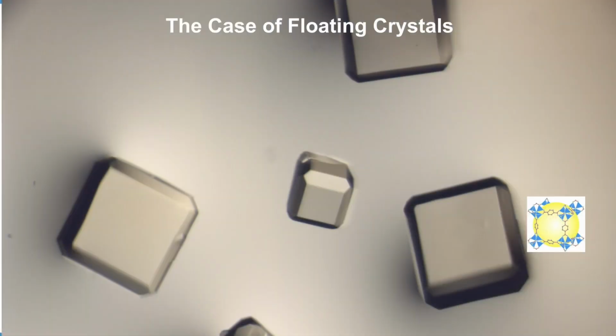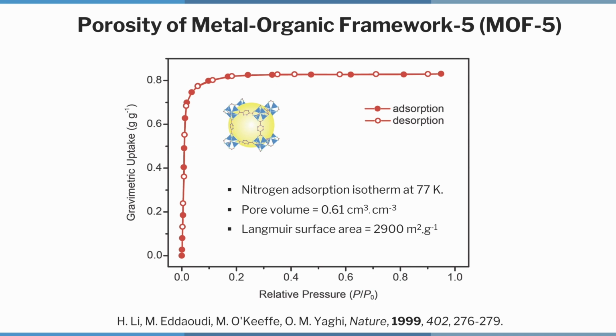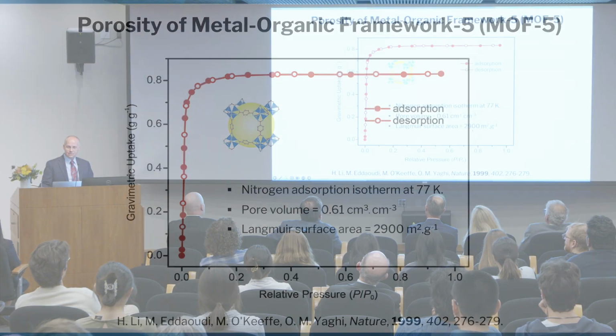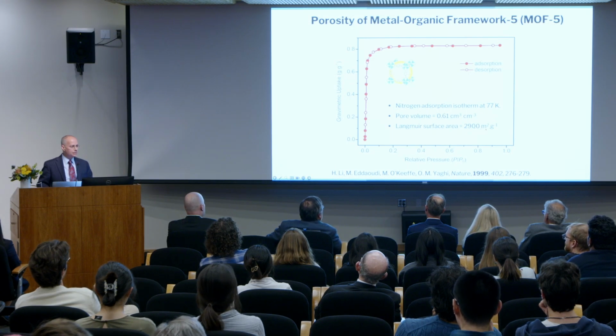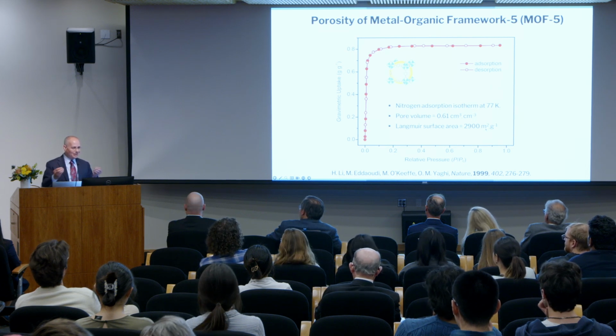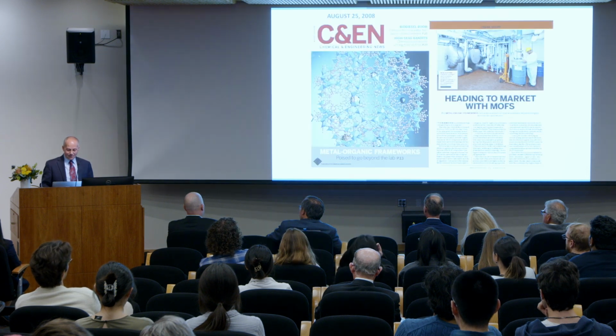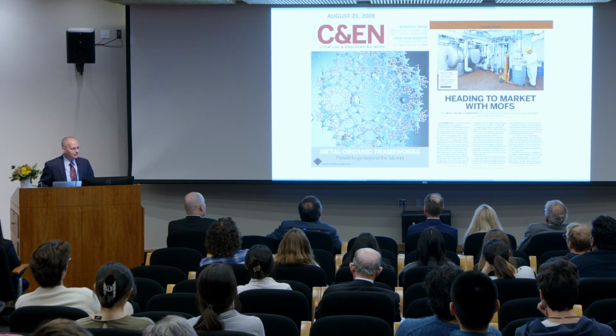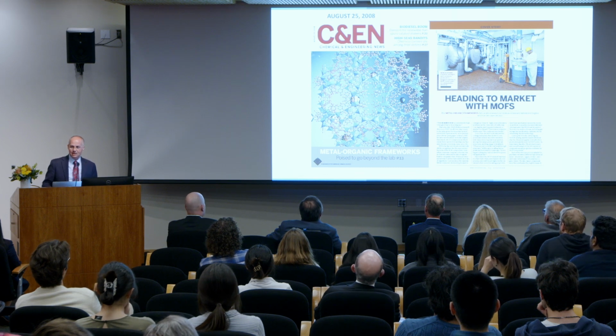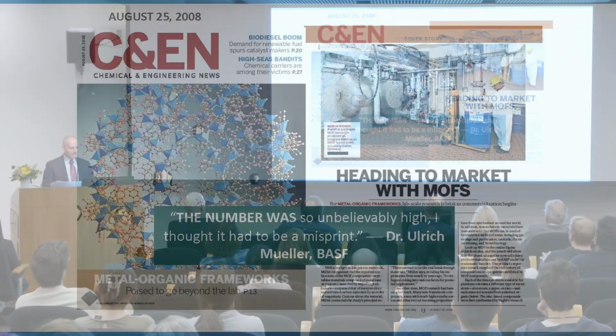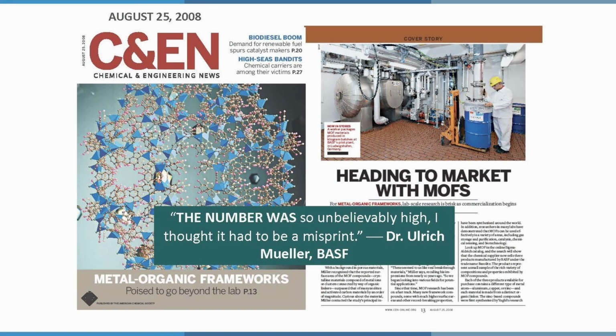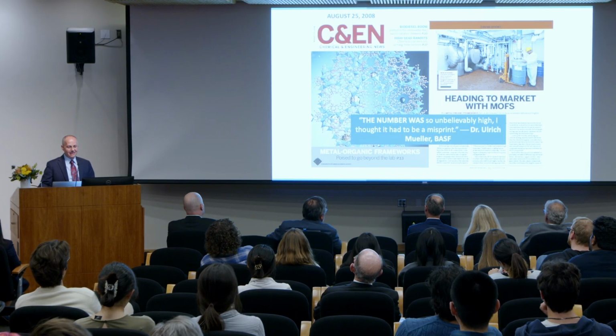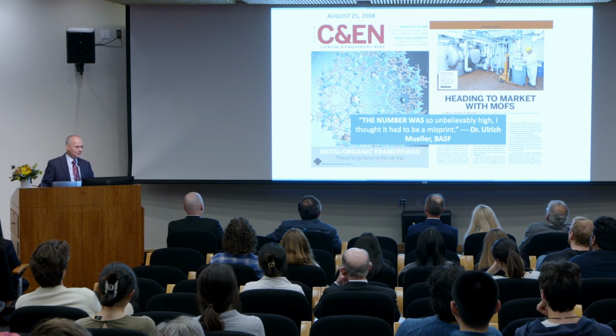this structure. And this structure, the reason it's so special is because it broke the surface area record of all materials for the last 1,000 years. It was so porous with a surface area of 2,900 square meters per gram. And just to give you an idea, now we are used to these high surface areas because of MOFs. My colleague at BASF, with whom I have collaborated over the last 17 years to scale up MOFs to multi-ton quantities, revealed in an article that was published in a chemistry journal that the number, that means the surface area number, was so unbelievably high, I thought it had to be a misprint. Okay, and that's how amazing that surface area was.